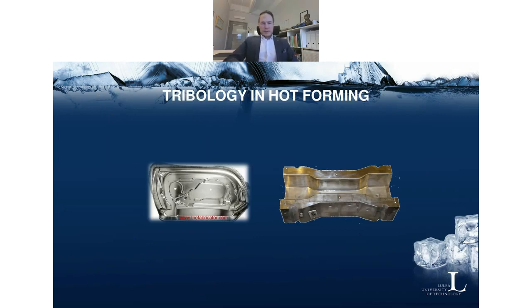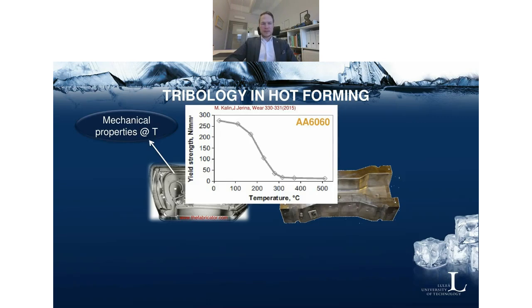A couple of words on hot forming and what needs to be considered, and I will give this example for an aluminium alloy, but it also applies to other workpiece materials. Of course, the mechanical properties of the workpiece material at the temperature you are looking for is very, very important. This is given now for a 6000 aluminium alloy, 6060 alloy in this case. And you can clearly see that the mechanical properties drop significantly after about 200 degrees Celsius. And if we're forming the material at, let's say, 400 or 450, there is not much of the yield strength left in the material at that state. That's, of course, one of the advantages to enable forming of complex geometries. But at the same time, that also makes the material very soft and very susceptible to transferring to another surface, the tool in this case.